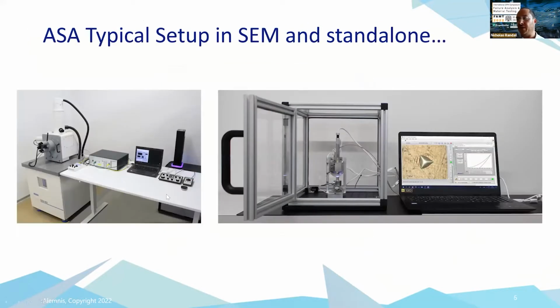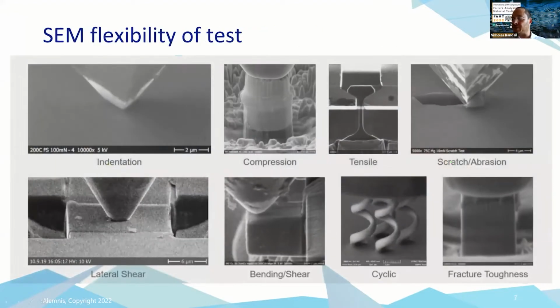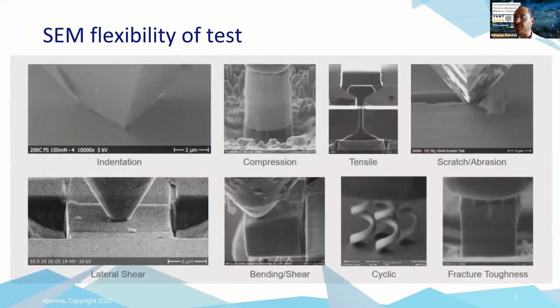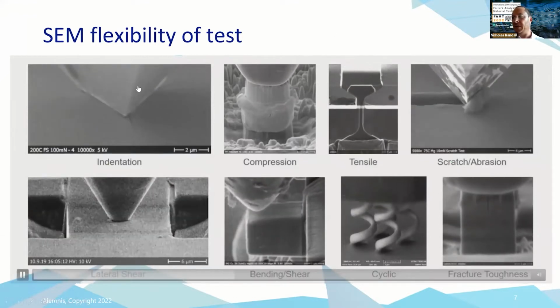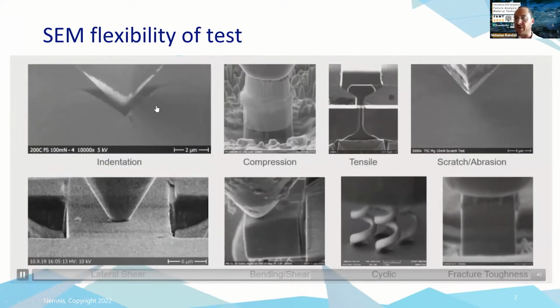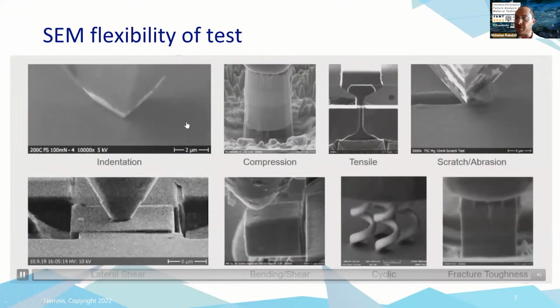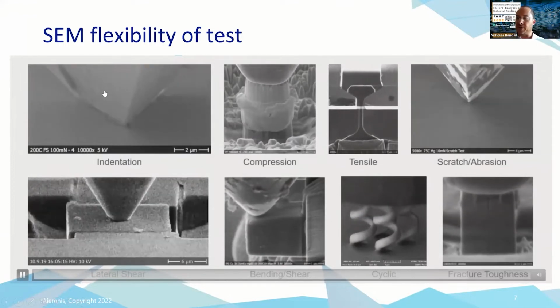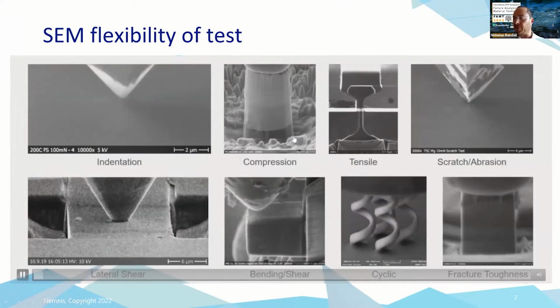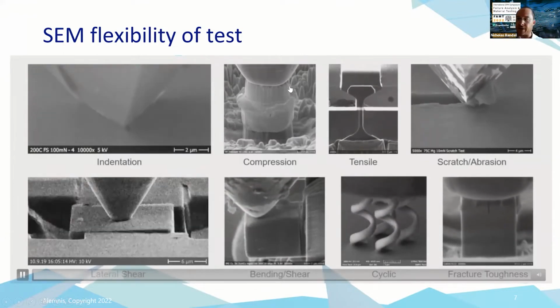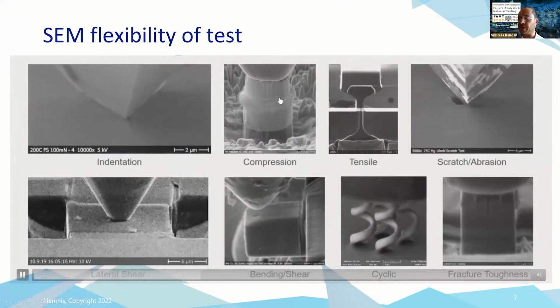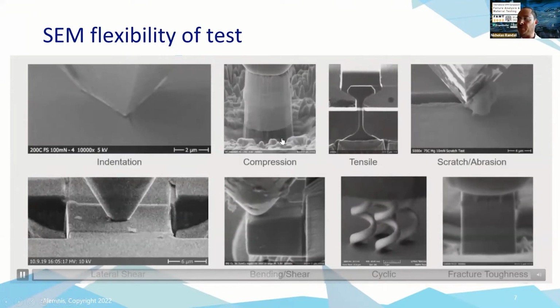We can either mount it in the SEM on the left here, or we can take it outside the SEM and use it as a standalone, very similar to a standard nano indenter mounted vertically. Here are some examples of how you might want to use this type of test. Top left is a single nano indentation, so conventional nano indentation where we're cracking the surface. This is actually gallium arsenide to measure the fracture toughness. Here we've got a micropillar of a 4-stack coating. There are 4 coatings here. We've cut a pillar and we're measuring the stress strain properties.